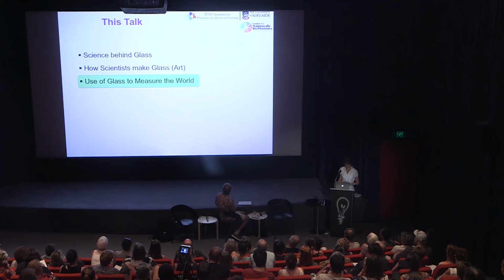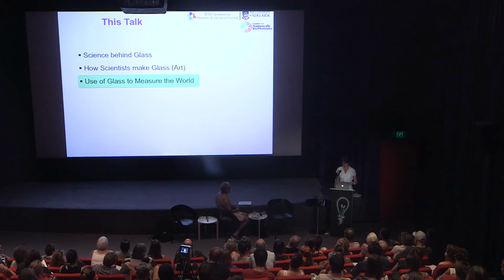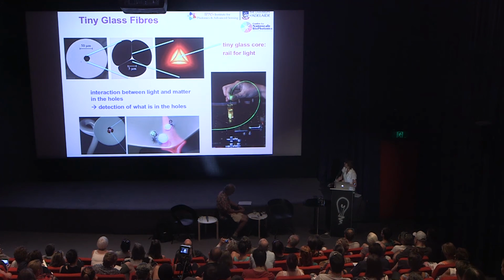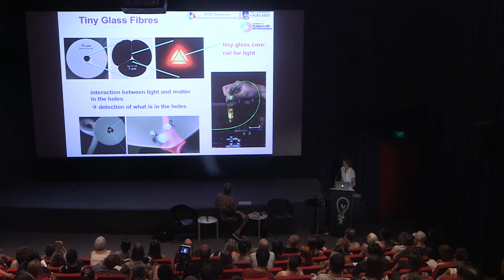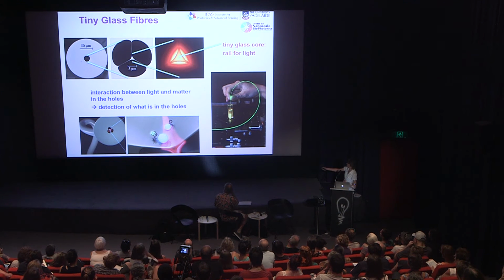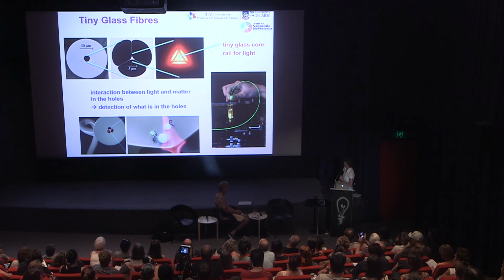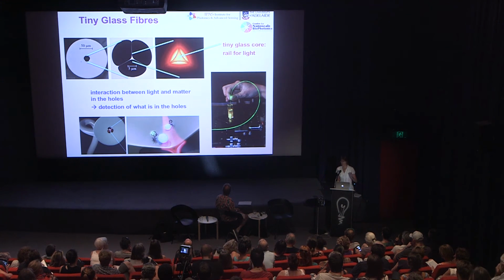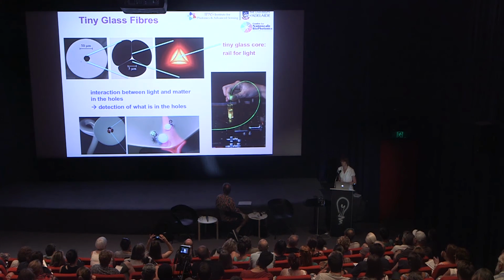Now just a few slides on how we use our glass fibers to measure the world. So you see here a fiber, you have seen the structure before. The black areas are air holes, and the gray areas are glass. So what's happening? Because of the index contrast, total internal reflection, that's very nice, we already learned about it today, is now happening in this glass core. So the light is traveling along the glass core, but the glass core is so small that it acts as a rail of light. It is shown here in this animation, so that part of the light is outside of the glass and goes into the air hole.